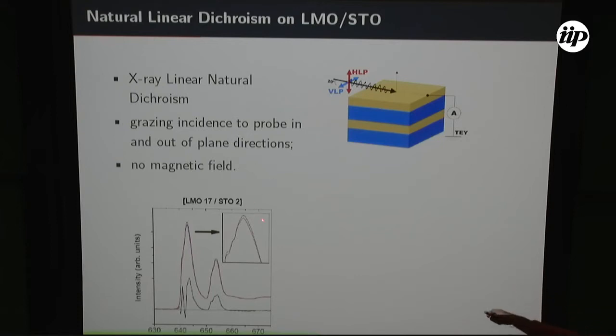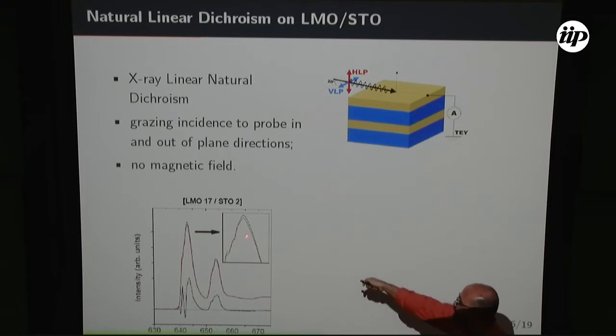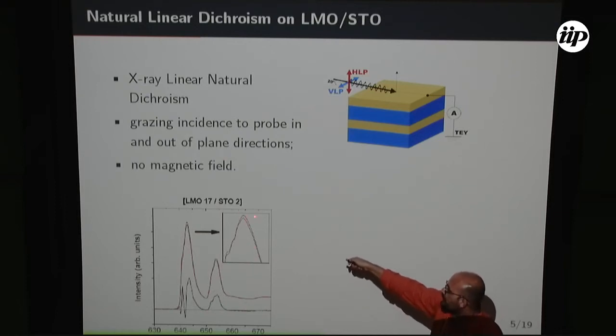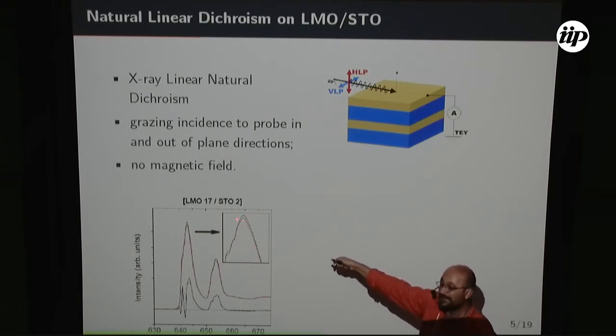Thus, in this case, the 3d, so here's a transition from the 2p of manganese to the empty 3d states of the manganese. So you have more empty states on the vertical and more electrons, more population on the horizontal. So with this, you know that from the crystal field splitting, that you are populating more the Z² orbital than the x²-y² orbital.